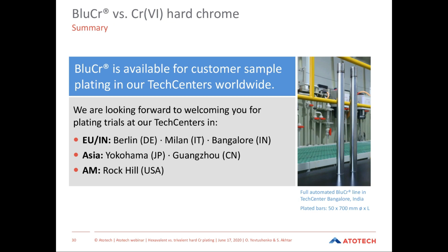Next question, can this new technology be used at the industrial level? Like, for instance, 40 centimeter diameter and 1.4 meter length bars? So going by the work we have done so far, we don't see any reason why you cannot industrialize it for such large parts. In fact, the customers we currently have operating are using the process for plating hydraulic bars. So there's no issue in terms of the size of bar that you are plating with blue chrome.